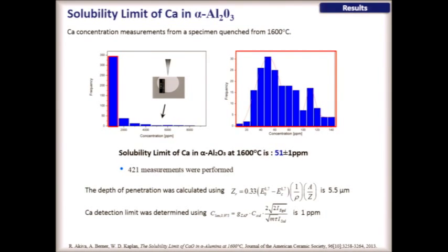This is the general measurement, the frequency of measurements, and concentration. If we zoom in this area, we have this massive peak and expand the histogram, you see this nice peak, and that's the solubility limit. And this is already information that's coming from the grain boundaries. So that's actually a measure of excess. Not an exact measure, because we don't know the exact overlap of the grain boundaries, but we don't care about that, because we can do that by TEM in a better way. This is the solubility limit, and it works out to be 51 ppm at 1,600 degrees C.